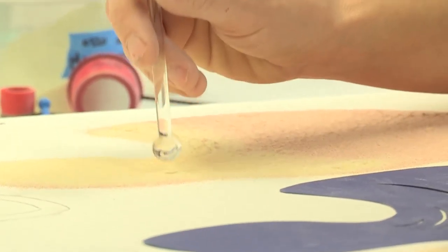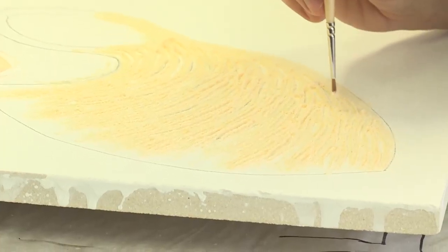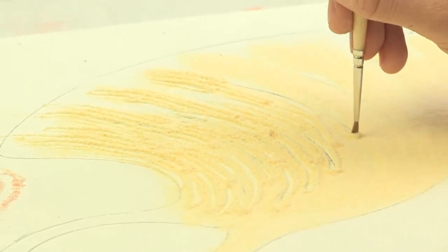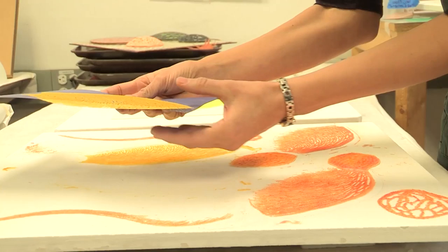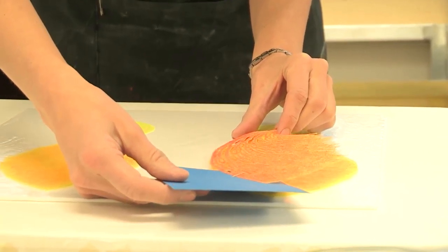One of the biggest challenges I had in the early stages was just the shrinkage of the material. As the powder heats, it squeezes in on itself. So if you're adding five or six different layers, those aren't going to match up by the time you get them fired, because as the glass squeezes, it shrinks and bends. So I really wanted to do some time trials, some shape trials, and work through those to get more predictable effects. I've been able to work through some of that through sheer trial and error.